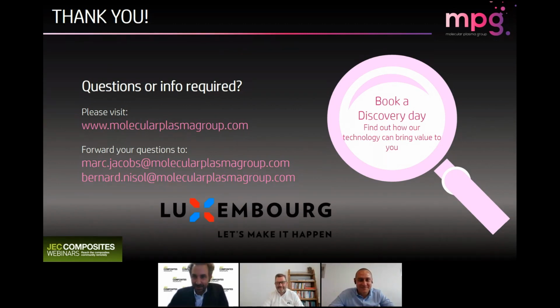Okay, another question from Malolan. Do you call air plasma as corona, or what is your definition for plasma and corona? So corona discharge to us is indeed a type of plasma, typically formed in open air, but not necessarily. With air plasma, you can have a dielectric barrier discharge of air, but that will still be a plasma full of streamers with high energy and high temperature compared to what we call a glow discharge and low temperature plasma. Now, corona is a very specific type of plasma indeed.